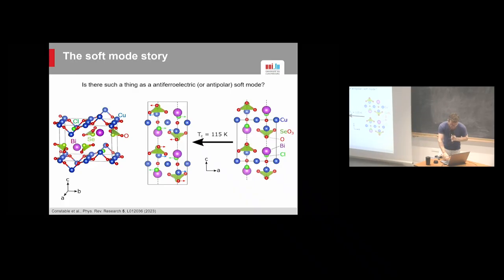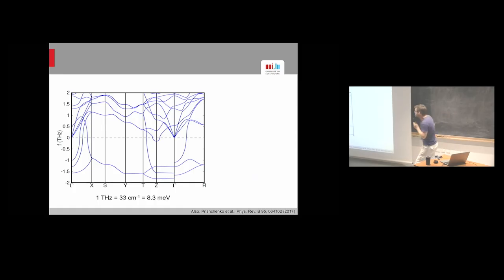So in terms of phonon bands, because we did that, this is what it would look like, calculated by first-principles, but it's also in the literature anyway. It's complicated. We want to pay attention to gamma, of course, the zone center, and to Z, the zone boundary that we are interested in. And what we see here in the calculation is a band that looks really flat.